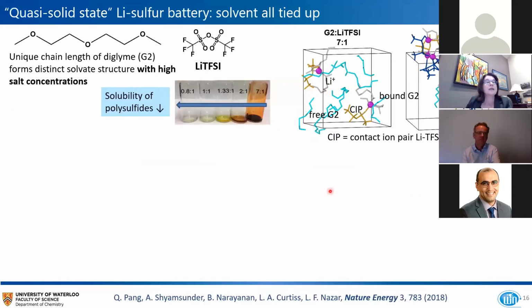So our initial attempts finally led us to what we think is a pretty great system. And effectively, we formed a solvate ionic liquid by using a diglyme, which is basically just an ether. But this particular diglyme has just the right length to wrap around the salt anion pair that is used as the salt in the electrolyte.